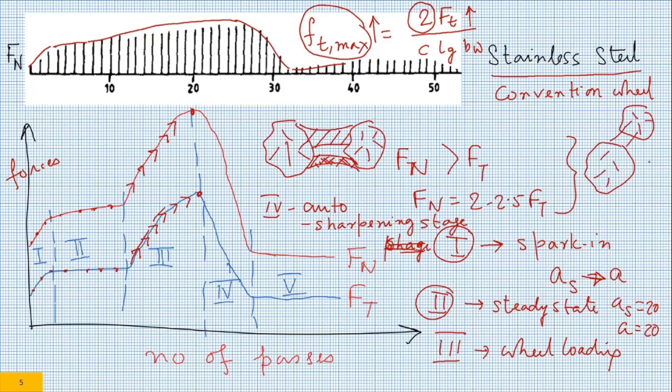So this is an outer grit. As more and more force is coming here, there would be bond fracture and this grit will come out. Not only the grit will come out, the loaded chip particle which was there at this particular intergrit space will also come out. So what is happening at this stage is that because of too much force, this outer layer of grits along with the loaded particles will come out.